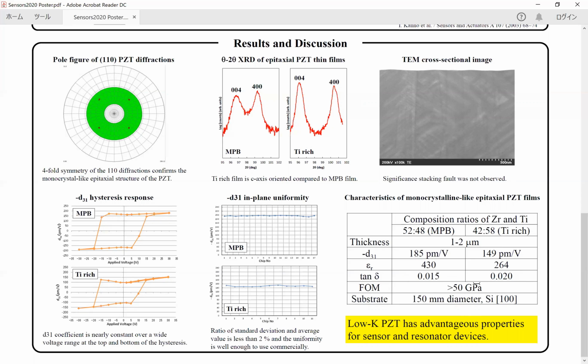This value is more than 40% higher than 35 gigapascal of the world's highest level commercial polycrystalline PZT thin film, and superior to 14 gigapascal and 34 gigapascal of aluminum nitride and scandium aluminum nitride, respectively. This high figure of merit also indicates that the low-K PZT can be beneficial for resonator device designs.